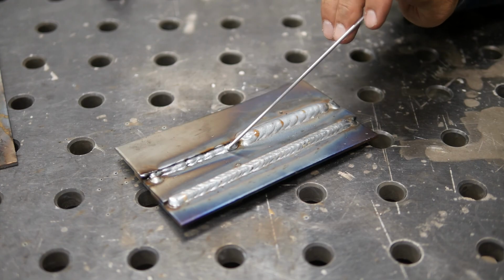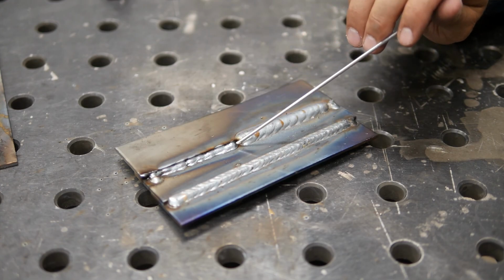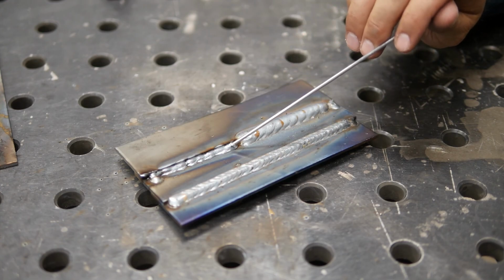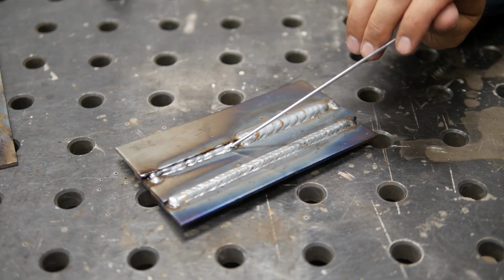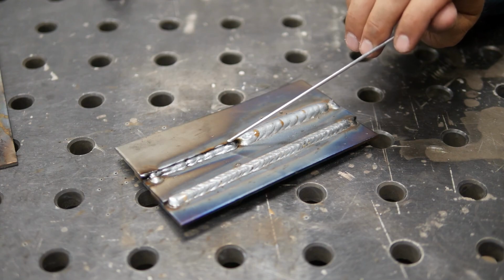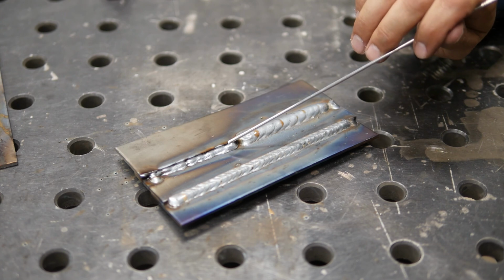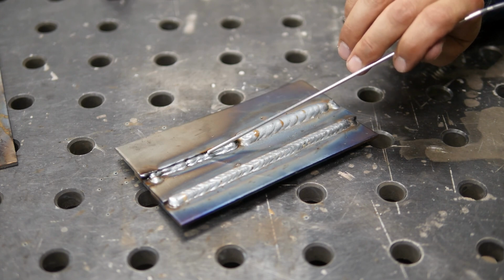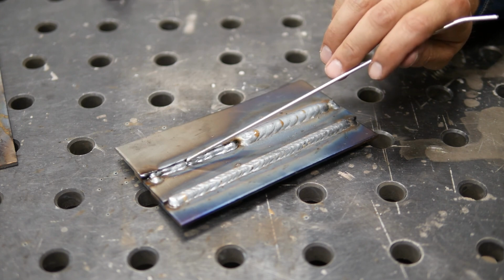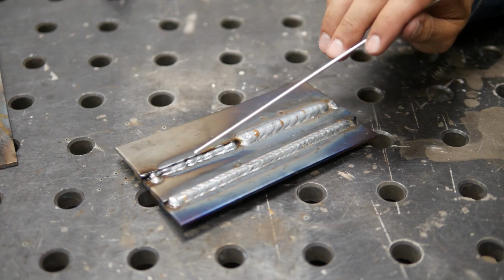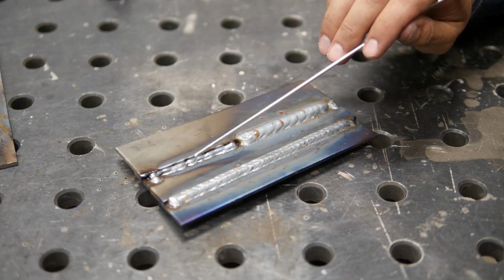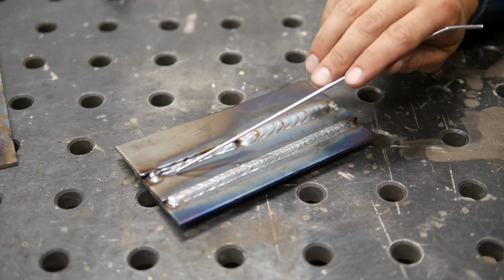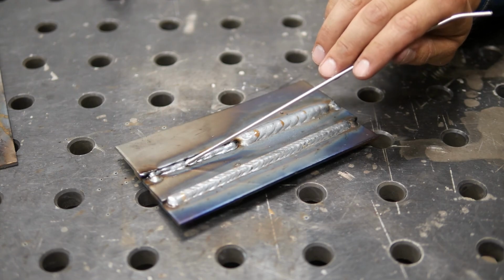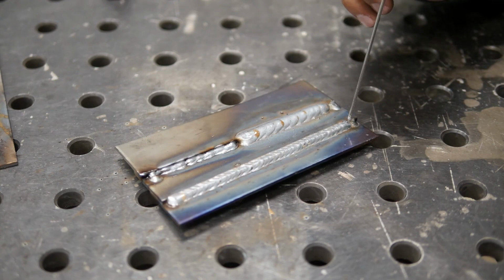On this side, the weld is too fast. What we want is we want an 1/8 inch weld. So I want to go from the root of the weld or the center of the two pieces up an 1/8 and out an 1/8. And you can see that it didn't quite get all the way to the top of the plate there. And in the right scenario, this one would fail prematurely, probably break right in the middle or maybe right there in the toe of the weld. So you got to work on your travel speed.